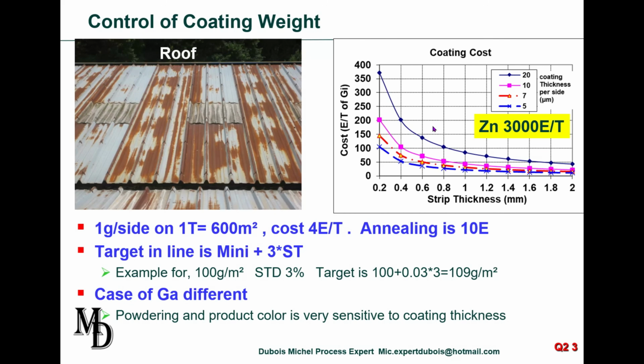You know that zinc today costs about 3,000 euro per ton. And if you look at the cost of this coating per ton of galvanized for different coating thicknesses, you see that the thinner the coating, the higher the cost. This is obvious because you have more square meters when you are running thin sheets. And you can clearly see that the difference between 20 and 10 micron is significant. Just to give you an idea, 1 gram of zinc per side on 1 ton is 600 square meters, but the cost is typically 4 euro per ton.